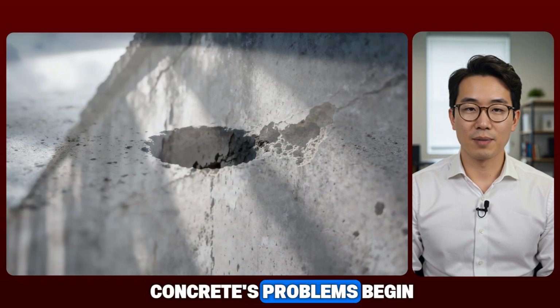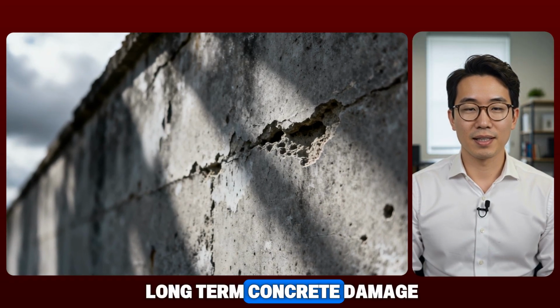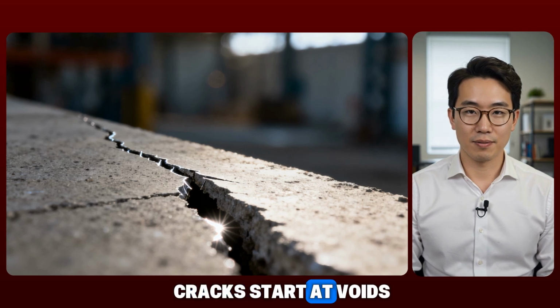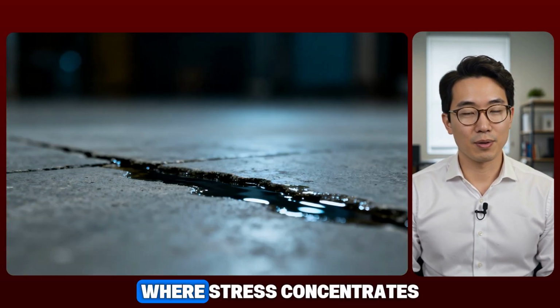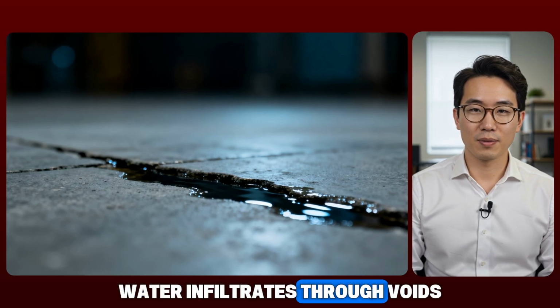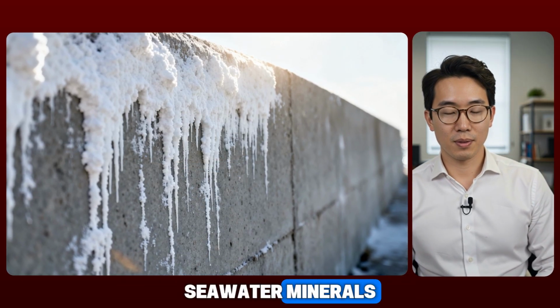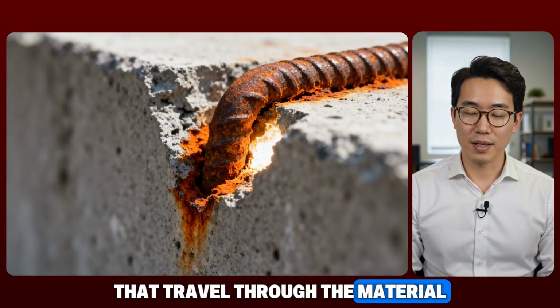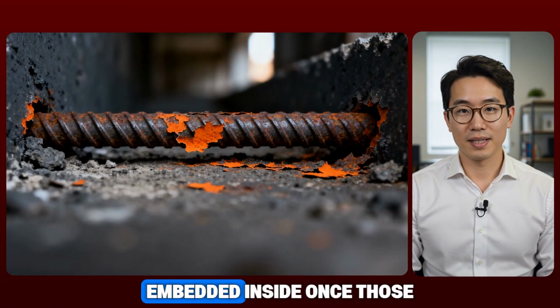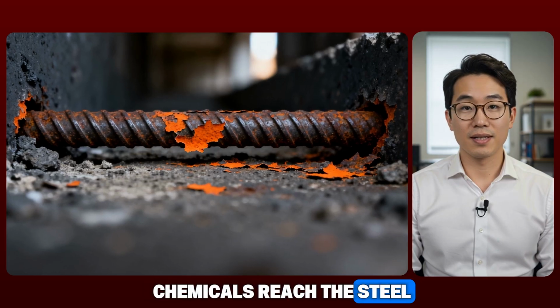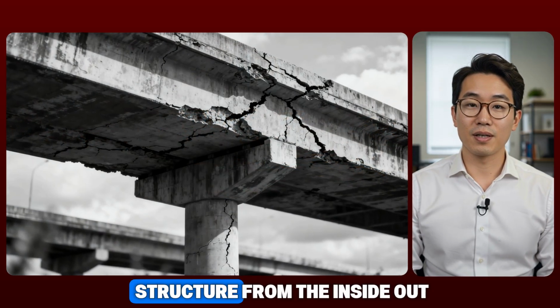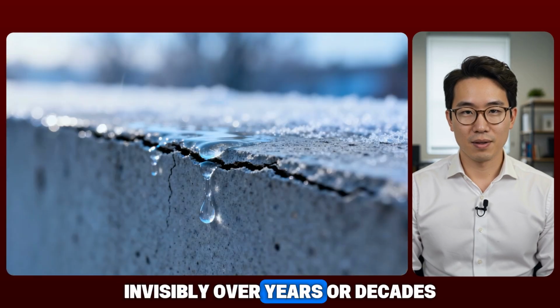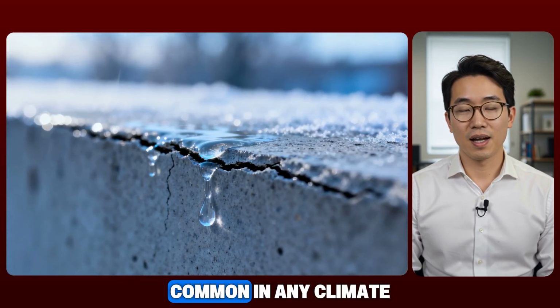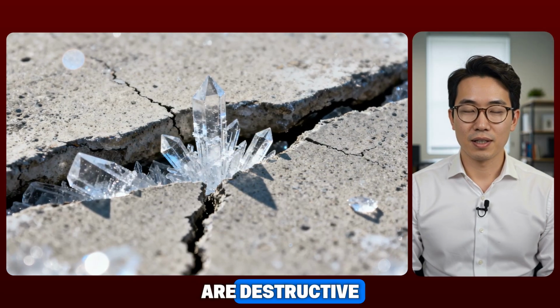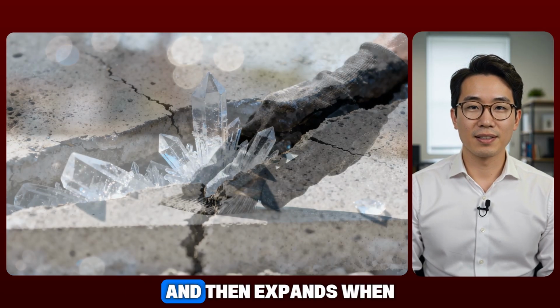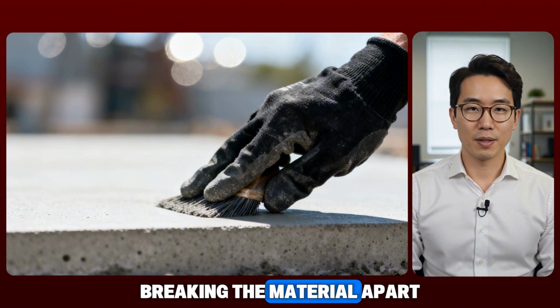Those voids are where concrete's problems begin. Nearly every form of long-term concrete damage traces back to them. Cracks start at voids because voids are points of structural weakness where stress concentrates. Water infiltrates through voids, carrying with it road salt, seawater minerals, and chemical pollutants that travel through the material until they reach the steel reinforcement bars embedded inside. Once those chemicals reach the steel, they cause corrosion that slowly destroys the structure from the inside out, invisibly over years or decades. Freeze and thaw cycles, common in any climate with cold winters, are destructive precisely because water gets trapped in voids and then expands when it freezes, breaking the material apart from within.